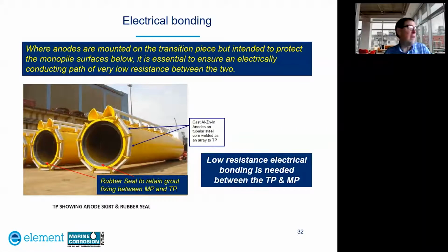So next, just want to say a few words about electrical bonding. So where anodes are mounted on the transition piece, but intended to protect the monopile surface below, it's essential to ensure an electrically conducting path of very low resistance between the two. So this photograph here shows the transition piece here with the rubber seal to retain the grout. So low resistance electrical bonding is needed between the transition piece and the monopile.